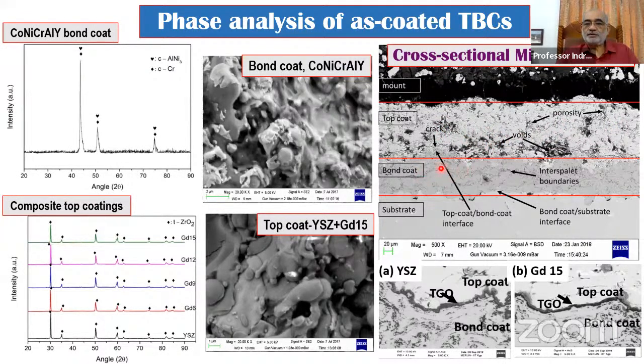But then you need a bond coat, you need a substrate. So obviously this cohesion here is very important, and the top coat has to connect well with the substrate because of the bond coat. So you have possibilities of creating 3-4 different layers, and each time you have to change from vapor deposition to thermal spray and so on. So it's a fairly cumbersome process, and the interface is fairly sharp. That's another major disadvantage, because of which spallation can happen.